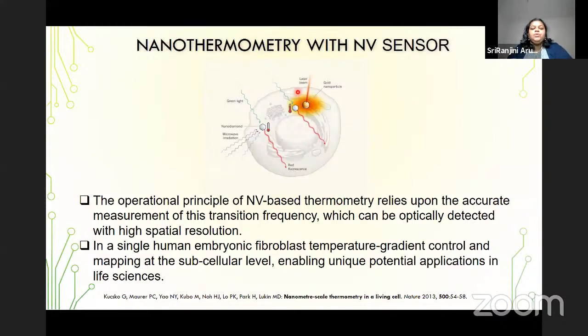Another application is to use it as a thermometer inside a cell. So we call it nanothermometry because these are nanometer in size, using the NV diamond. The operational principle is you implant it inside a cell, and then there is a transition in frequency, which can be optically detected with high spatial resolution. So by doing the ODMR and mapping the fluorescent signal, one can interpret the temperature correlation. In this work, it is done with a collaborator.